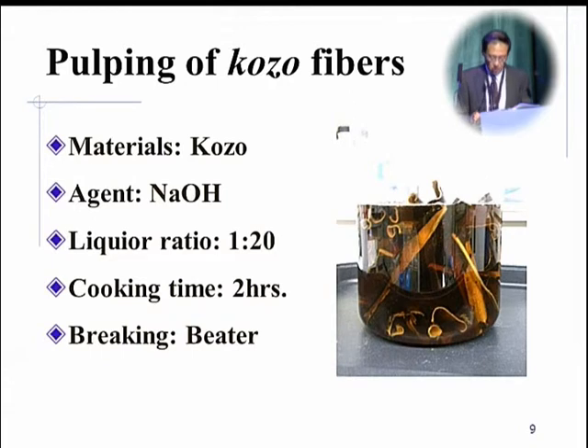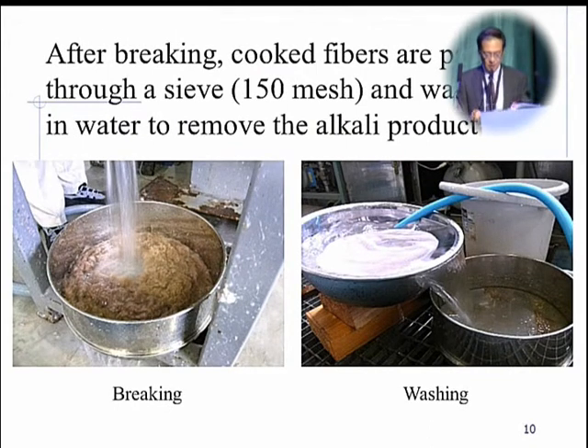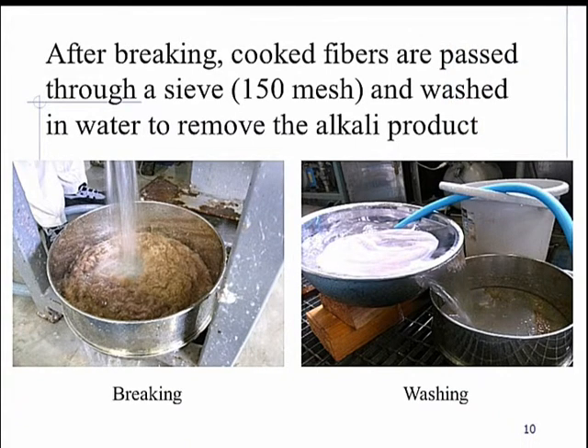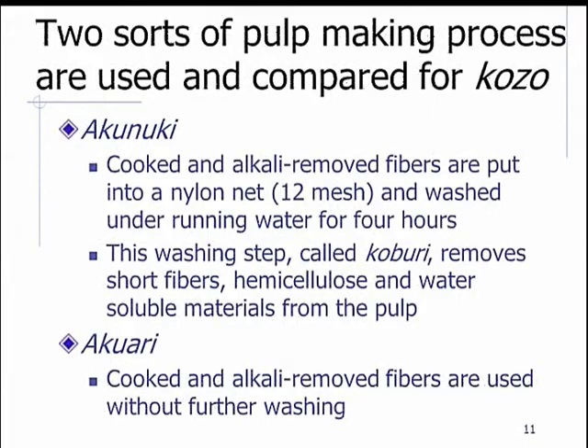Preparation of kozo. Kozo fibers are cooked for 2 hours in water containing 0.5% caustic soda and then broken up using a beater. After passing through a sieve, cooked fibers are washed in water to remove the alkali product. In this study, two sorts of pulp making process are used and compared for kozo: akunuki and akuari.